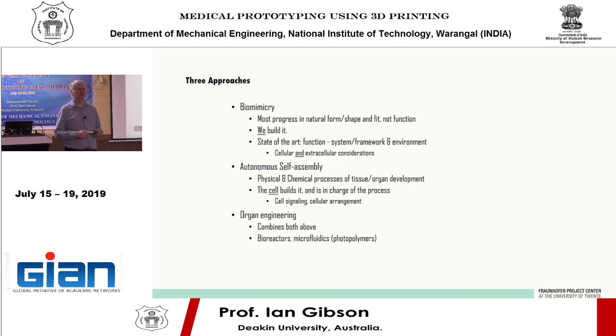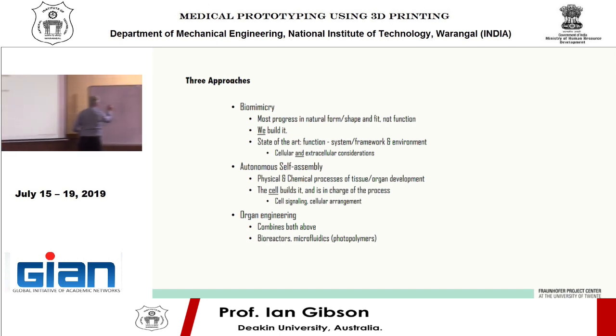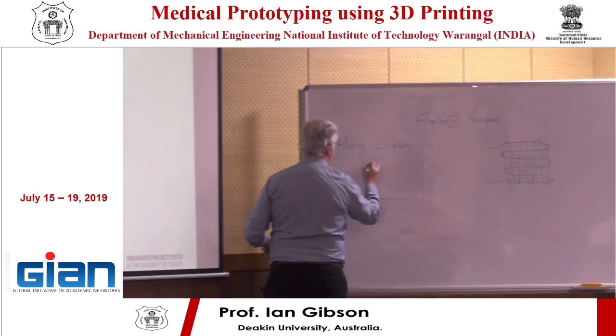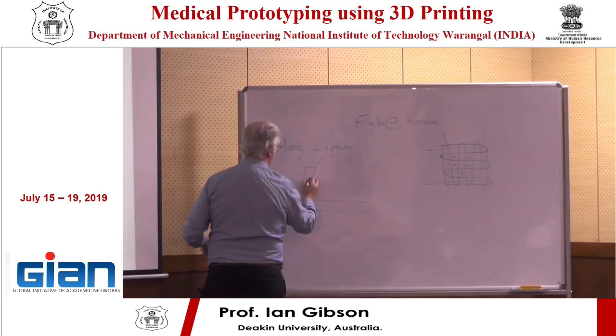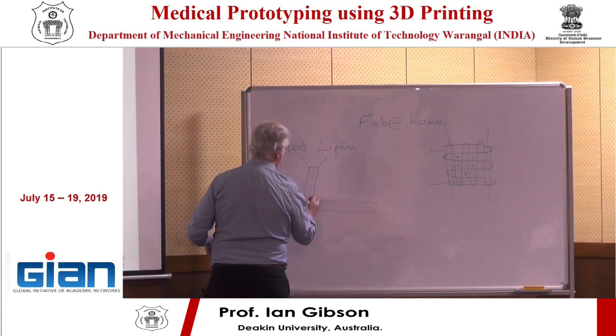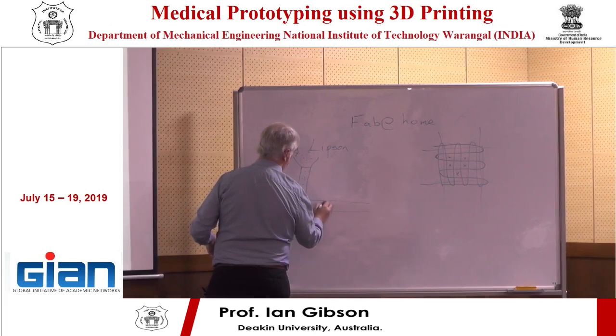Now, I mentioned etching of the scaffold. One of the reasons that we etch the scaffold is because when we incorporate the calcium phosphate into the polymer, it goes into the middle of the polymer feed. So you end up with an extrusion. You extrude from the nozzle. So here's the nozzle, here's the extrudate. What happens is in the nozzle, you'll have particles of TCP being carried by the molten PCL.